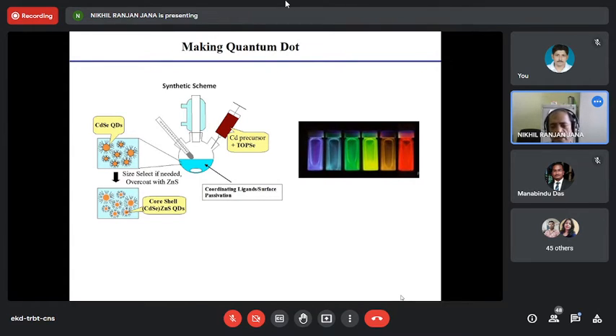Selenium will react with cadmium. Actually, the selenium precursor and cadmium precursor degrade and convert into cadmium units and selenium atomic units. They combine to make cadmium selenide clusters, nanoparticles, aggregations. And surfactants are there. You see the hydrocarbon-based surfactant, they cap the surface. So all is happening: nucleation, growth, quantum dot formation at high temperatures, within a few seconds to a minute.